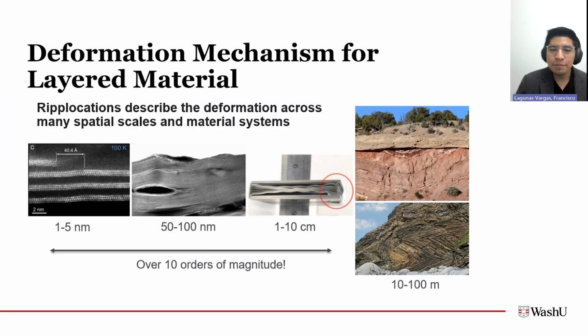So that's really exciting, that we can see the movement of these different types of defects in the TEM. To conclude, the fact that we're able to see these Ripplocation defects at these scales is really incredible, because this type of defect has been used to describe defects in material systems over 10 orders of magnitude in spatial scale. Here we're looking at some of the smallest possible mechanical scales, between 1 to 5 nanometers. But you can see we observed similar things in FIB lamella that we made of these samples, on the order of 100 nanometers.